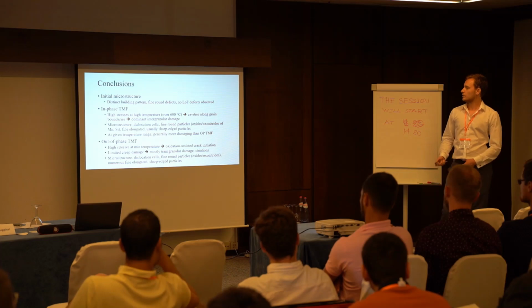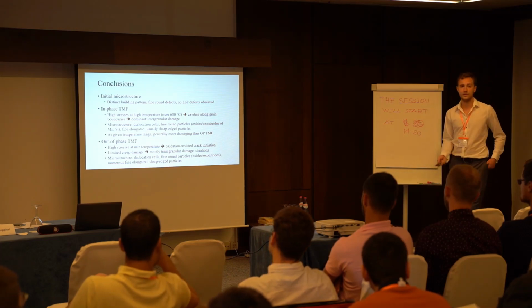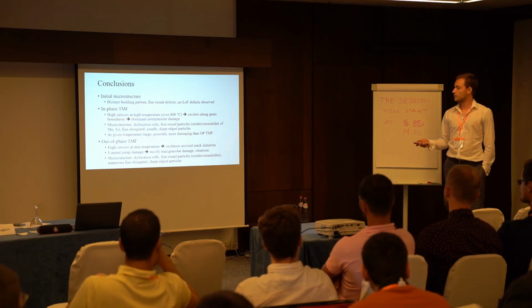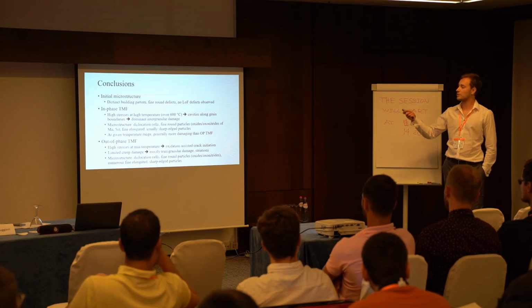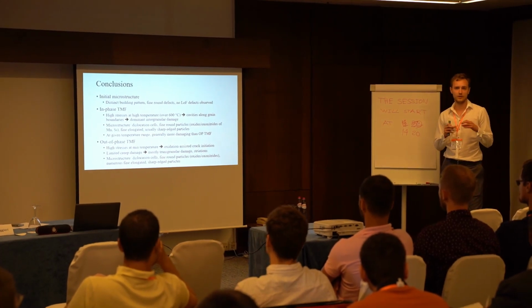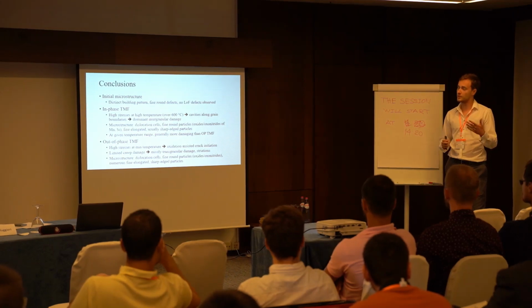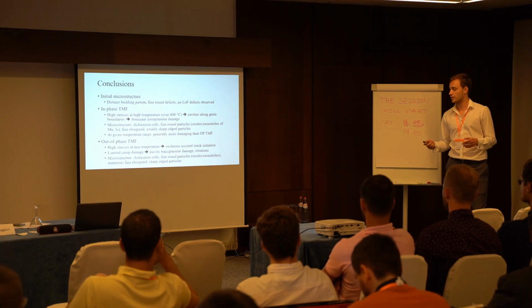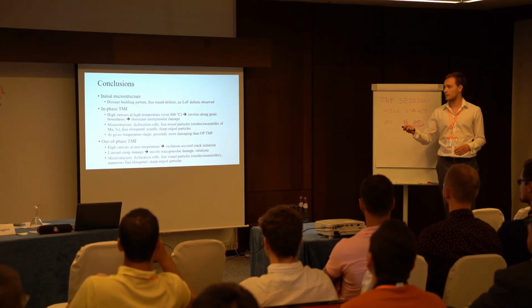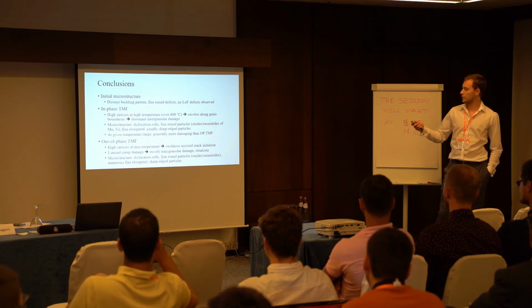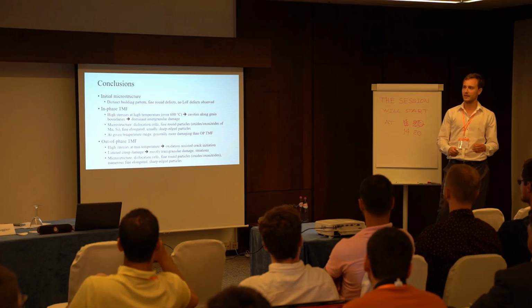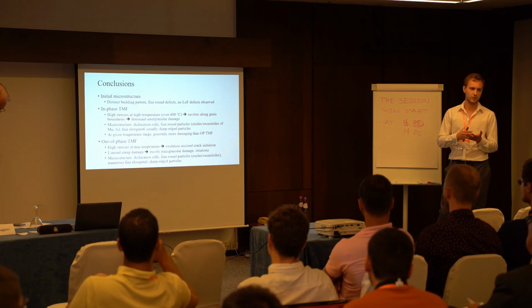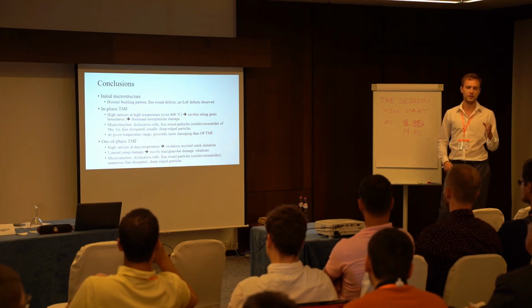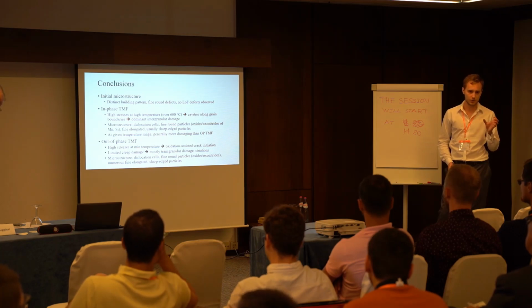Regarding the microstructure, the dislocation cells were there, and they were still quite stable. We had fine round particles still in the microstructure, and these newly precipitated particles, which were elongated, nucleated primarily at the grain boundaries and were also sharp-edged. We also saw that at the given temperature range, the in-phase was generally more damaging than out-of-phase. The reason for the cyclic softening we observed was that due to the huge internal damage, there was gradual reduction in the cross-section of the material, which led to a decrease of the stress levels we needed to impose the same strain amplitudes.